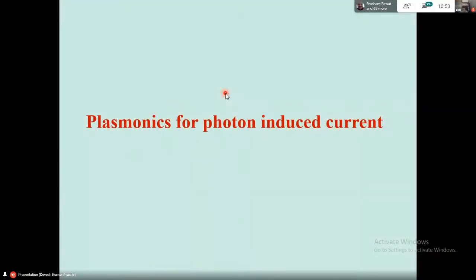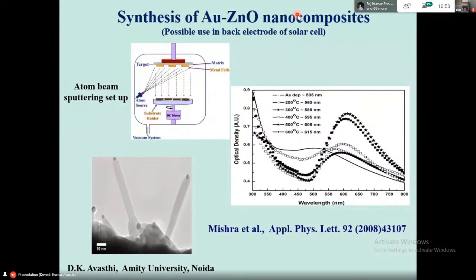Now, plasmonics for photon-induced current. This is also an interesting thing. I will show some results. We made a gold zinc oxide nanocomposite film, made by an atom beam sputtering setup. Here, a 2-inch atom beam is bombarded on an insulator, which is a matrix of ZnO, with some metal pieces of gold. By sputtering, the atoms and molecules come here, and by a self-assembly process, a nanocomposite film is made. That means gold nanoparticles embedded in ZnO are formed, and this is a TEM picture to show that in some conditions you have a zinc oxide nanorod, at the top of which a gold nanoparticle is sitting.